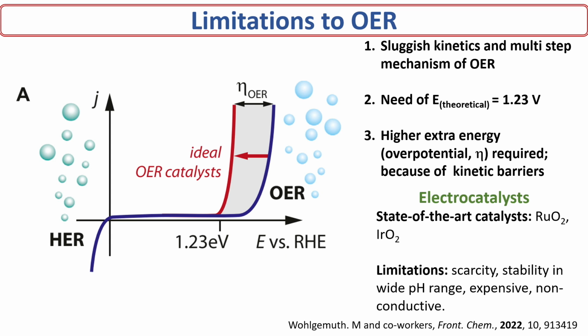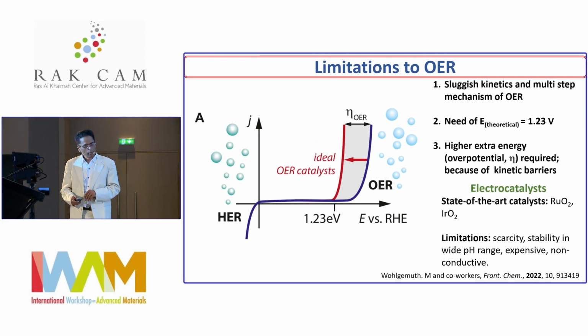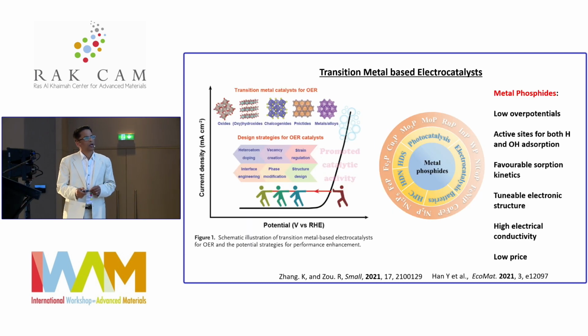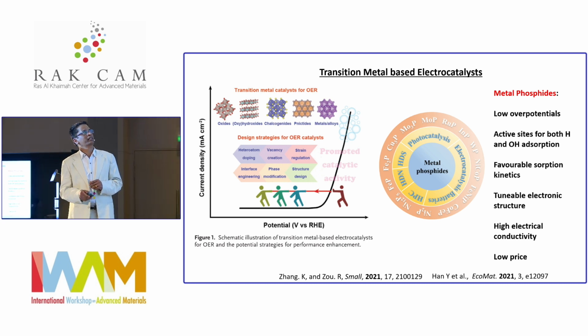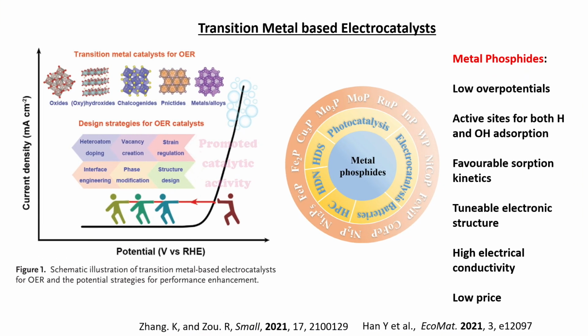But if you have the state-of-the-art catalysts, ruthenium oxide and iridium oxide, people are using them in high pH conditions. Again, the problems are cost, scarcity, and stability in a wide pH range, and it's also expensive and non-conductive. So going for non-expensive metals, particularly transition metal-based electrocatalysts, is getting a lot of attention. People use metal oxides, oxyhydroxides, chalcogenides, pnictides, and metals and alloys. Various design strategies for oxygen evolution reaction catalysts are used: introducing heteroatoms or vacancies or strain or doping, and even interface engineering and phase modification, to get higher activity and reduce the overpotential of this material.